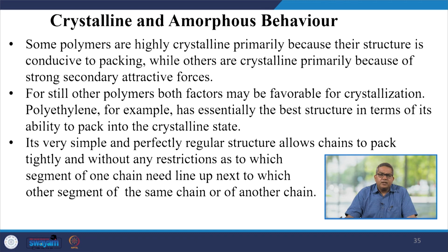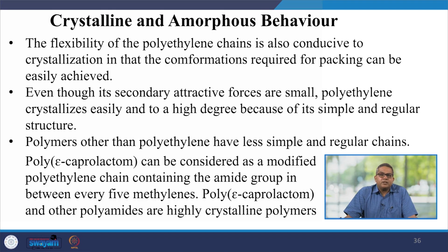Let us take the example of polyethylene. It is essentially the best structure in terms of its ability to pack into the crystalline state. Its very simple and perfectly regular structure allows chains to pack tightly and without any restriction as to which segment of one chain need line up next to which other segment of the same chain or of another chain. The flexibility of the polyethylene chain is also very conducive towards crystallization in the conformation which may be required for packing. This can be easily achieved even though the secondary attractive forces are small. Polyethylene crystallizes easily and to a high degree because of its simple and regular linear structure. Polymers other than polyethylene have less simple and regular chains.